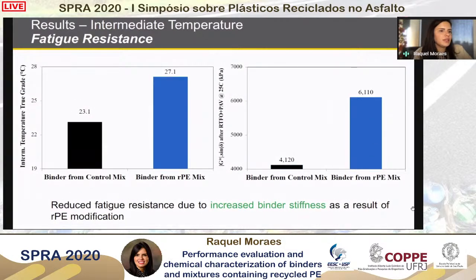And here we have fatigue. We also can see that we have a reduced fatigue resistance due to increase on the binder stiffness, a result of the recycled plastic incorporation.